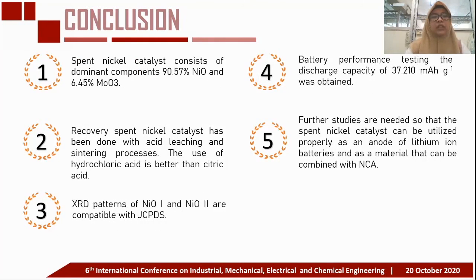And the last, for conclusion: first, spent nickel catalyst consists of dominant components of 90% nickel oxide and 6% molybdenum trioxide. And second, recovery of spent nickel catalyst has been done with acid leaching and sintering process. The use of hydrochloric acid is better than citric acid. Then the XRD patterns of NiO 1 and NiO 2 are compatible with JCPDS. Then battery performance testing, the discharge capacity of 37.210 mAh per gram was obtained. Finally, further studies are needed so that the spent nickel catalyst can be utilized properly as an anode of lithium-ion batteries and as a material that can be combined with NCA.